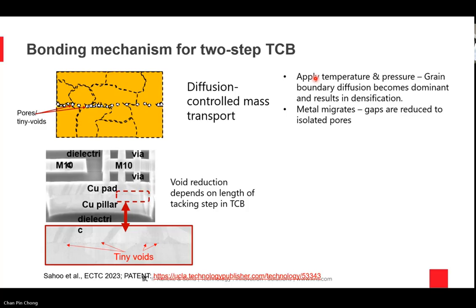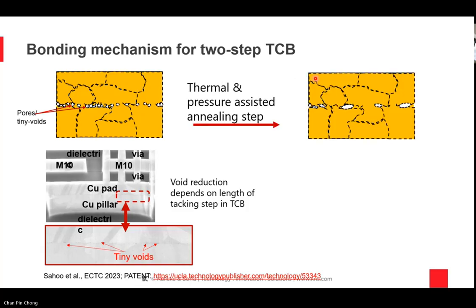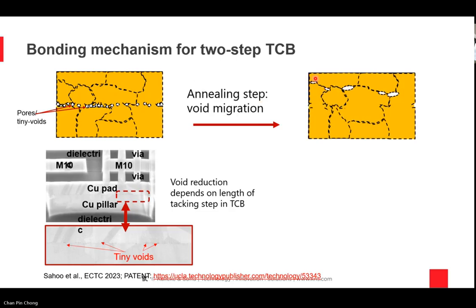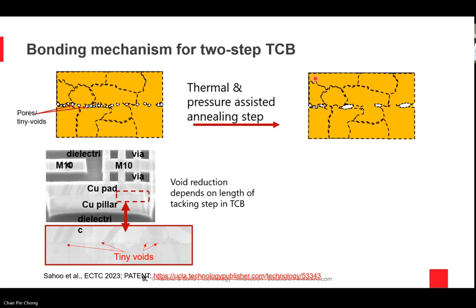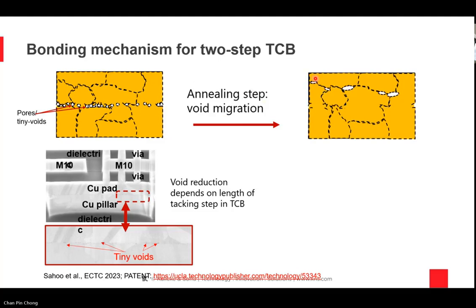Depending on the microstructure of the material, if one material has a higher diffusivity than the other, or there are more grains in one because of differences in texture and so on, the dynamics of the void formation and the void migration will differ, as shown on the right-hand side.